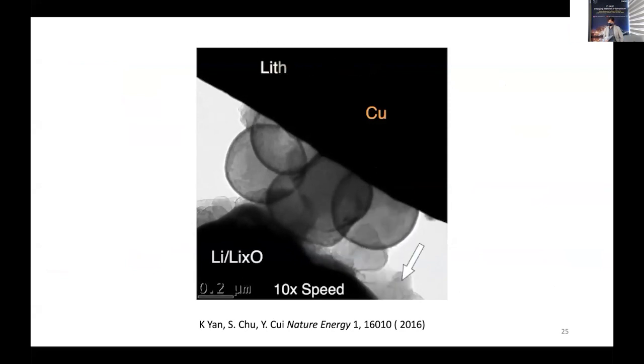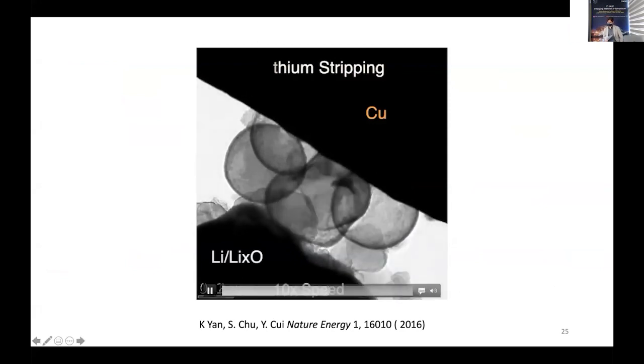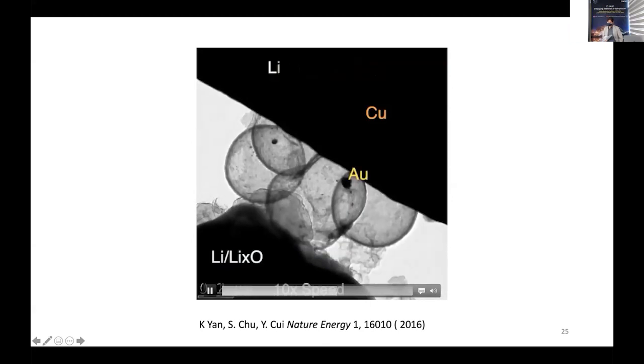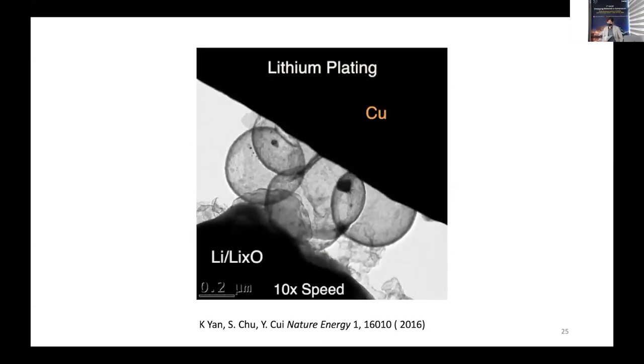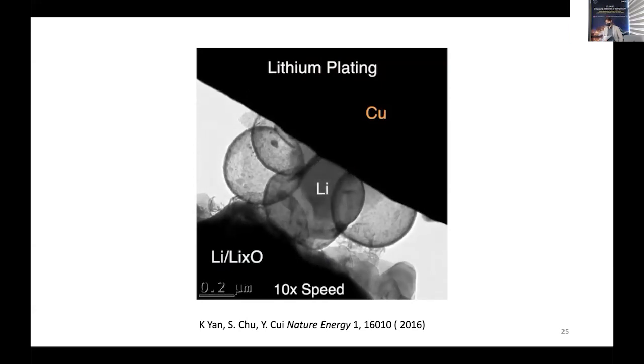And then once you strip lithium away, the gold nanoparticle comes back, but at a different location though, it also breaks into some tiny particles instead of the initial one as a single particle. This is confirmed. You strip lithium away, this gold kind of supersaturates and precipitates out. They can have multiple nuclei right there.